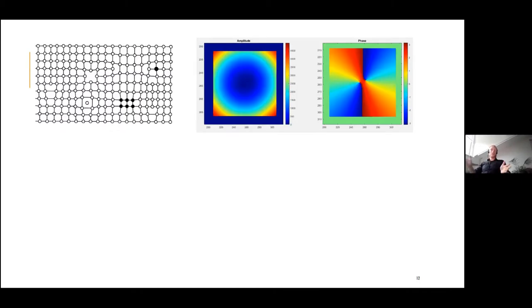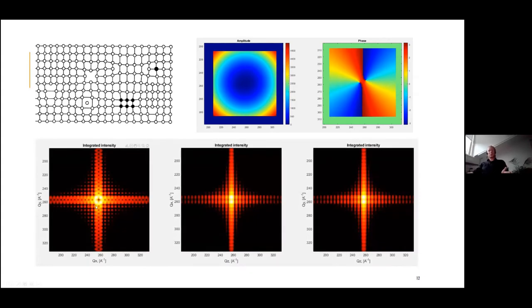Or there could be other defects like point defects, some topological defects like dislocations, which can be simulated like vortex fields inside the phase. So basically there are points of zero intensity and the phase is not defined there. So it goes to 2 pi values around this point, forming such vortices. And this is how the dislocation looks like in the crystal if you reconstruct the phase from the phase retrieval, and the diffraction starts to split and all kind of interesting effects can appear.